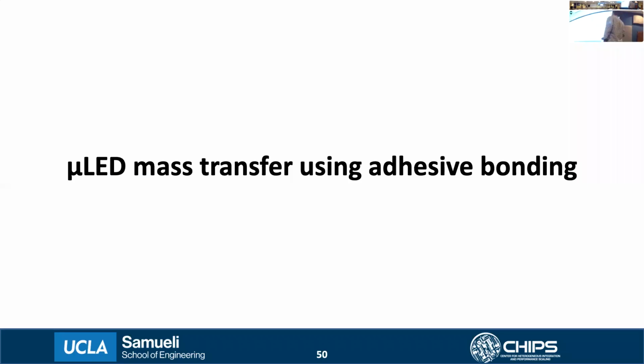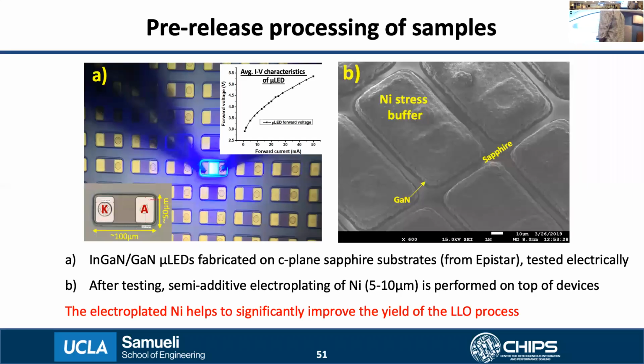So now let me move on to the experimental section of showing micro-LED mass transfer using adhesive bonding. Here in slide 51, on the left side optical image, you can see the prefabricated micro-LEDs on the sapphire substrate that we obtained from a commercial manufacturer. And here you also see me probing the device and the VI characteristic.